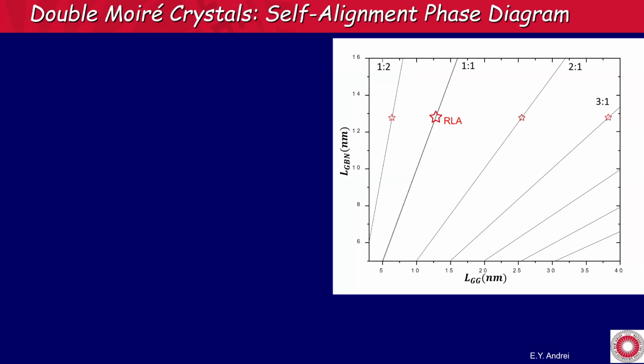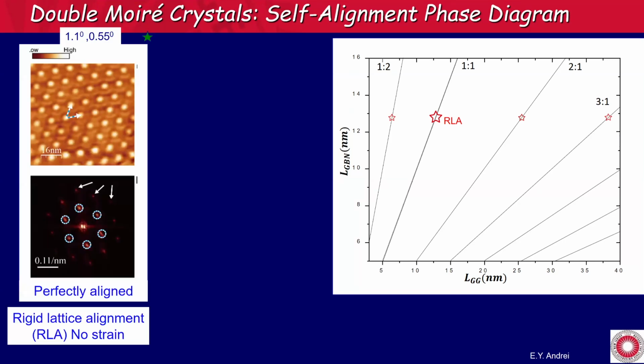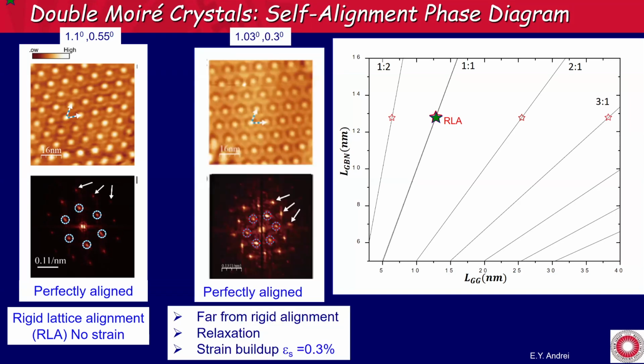Now, by the way, rigid lattice alignment cannot happen. You don't have a point of rigid lattice alignment if you have 3 identical layers, like 3 graphene layers on top of it. You have to have 2 and 1 or something like this. So, okay. So now here we have a sample that's exactly perfectly rigidly aligned, no strain in it. But then we have another sample. And this one is completely off that rigid lattice, but it's still perfectly commensurate.